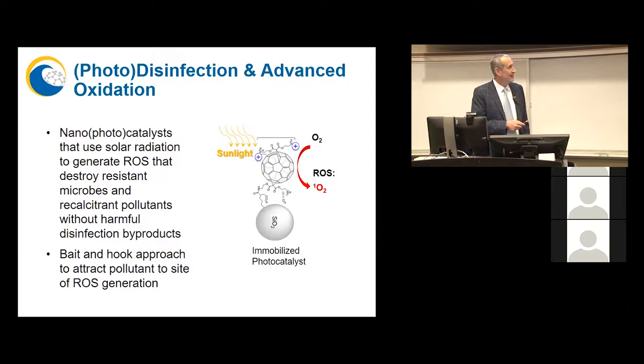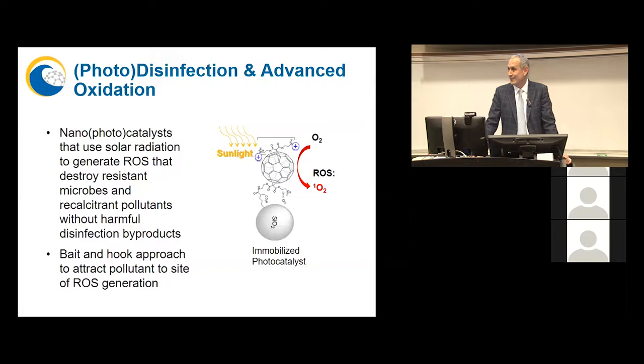Essentially, if irradiated by sunlight, the compound or molecule is excited to a triplet state. And then that triplet state energy gets transferred to molecular oxygen. It actually causes a change in the spin of one of the electrons, generating singlet oxygen. Singlet oxygen is a reactive oxygen species. It's not as strong an oxidant as the hydroxyl radical that titanium dioxide and other semiconductor-type photocatalysts produce, but nonetheless, it's good enough to kill bacteria.